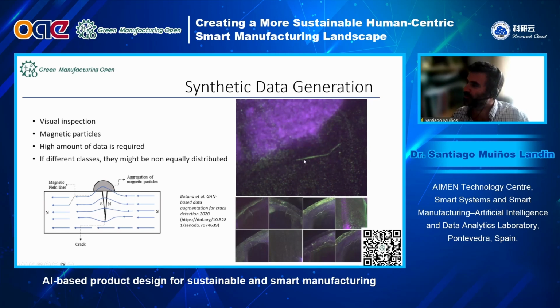And you can see these cracks like that if you put these pieces under a bath with magnetic nanoparticles. This is a quite standard technique in order to detect cracks. You put the metallic part in a bath with these magnetic nanoparticles, and if you magnetize the part, they tend to accumulate where you have an inhomogeneity in the magnetic field, so they accumulate in this region. And if you put some UV light over these pieces after you take them out of the bath, then they shine and they look like something like this, so that you can detect these cracks by this accumulation.